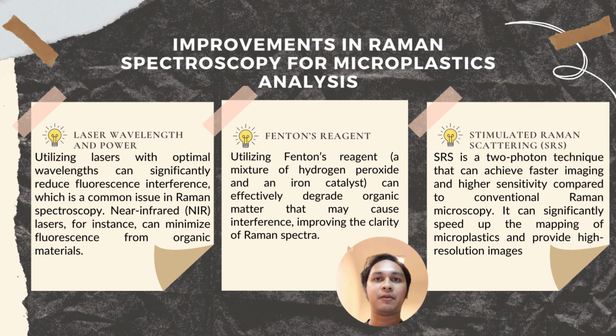The next step is we use the Fenton agent. What is Fenton agent? Fenton agent is a mixture of hydrogen peroxide and an iron catalyst which can degrade the organic matter that interferes with the spectra. So when we remove the interference, we can have a high intensity of spectra. Lastly, we can use stimulated Raman scattering (SRS). SRS is a two-photon technique that can achieve faster imaging and high sensitivity compared to conventional Raman spectroscopy. It speeds up the mapping of microplastic and gives high resolution images.